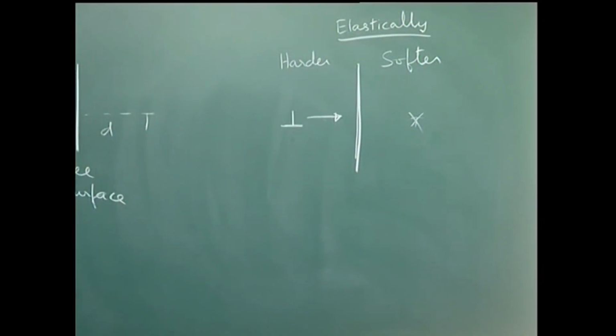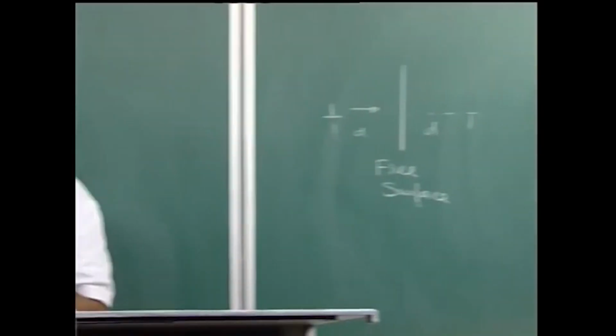That means that such kinds of effects also seem to play an important role in the strengthening of these bilayers, and they have also been attributed to give some additional effect to the hardening which is seen in these bilayers, which we have seen approaches almost the theoretical shear strength of the material. And additionally, of course, some common mechanisms which are observed in the case of large grain size materials, like dislocation pileup and bowing of dislocations, which is like the Orowan bowing, are also observed, but now we have to note that this can only occur at larger bilayer periods.